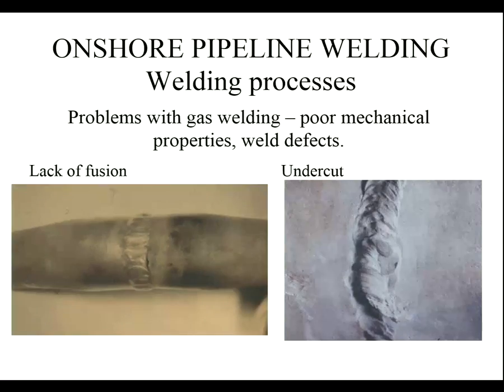And you have problems with those welds. So a very common defect in welds is lack of fusion. You can see that lack of fusion defect there. So what does lack of fusion mean? You put the two parts together, you make the weld, and the weld wanders too far away from one of the two parts, so you don't heat it. So it doesn't melt and it doesn't fuse with the weld pool. And it looks a bit like a crack, but it's really a processing defect. It's not a crack. It's not a sharp defect like a crack. But that has to be repaired because there will be a leak with that.